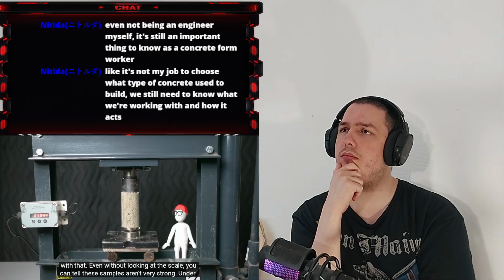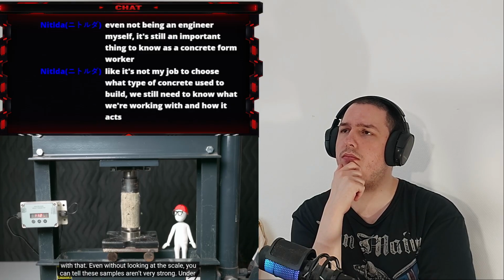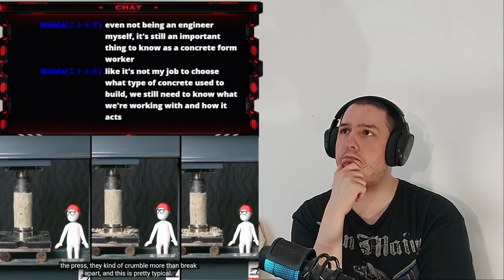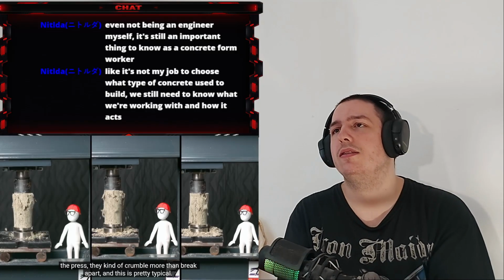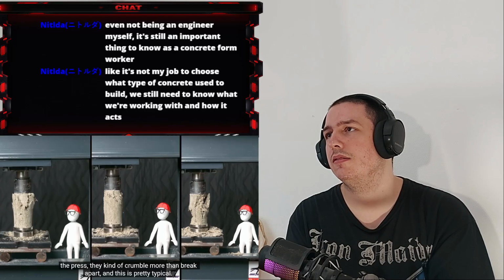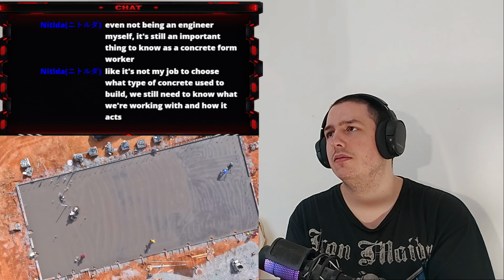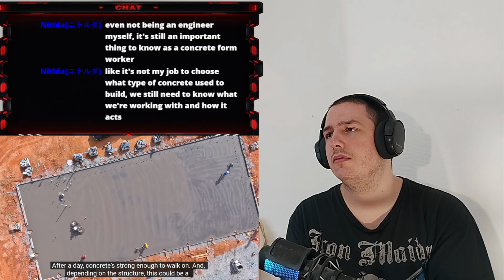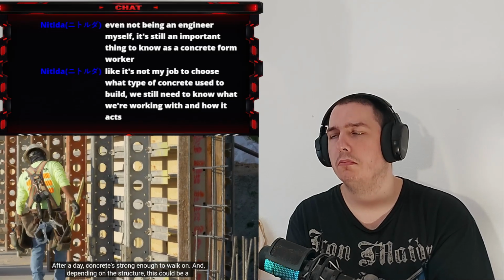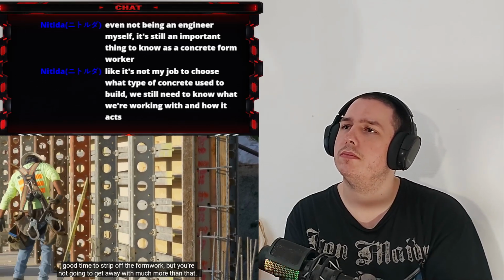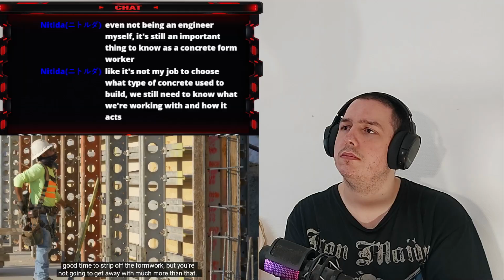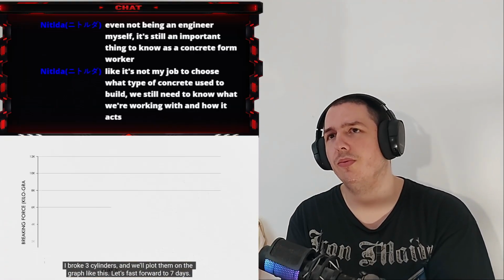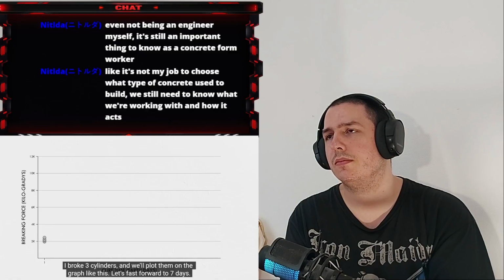Even without looking at the scale, you can tell these samples aren't very strong. Under the press, they kind of crumble more than break apart, and this is pretty typical. After a day, concrete's strong enough to walk on, and depending on the structure, this could be a good time to strip off formwork, but you're not going to get away with much more than that. I broke 3 cylinders and we'll plot them on the graph like this.